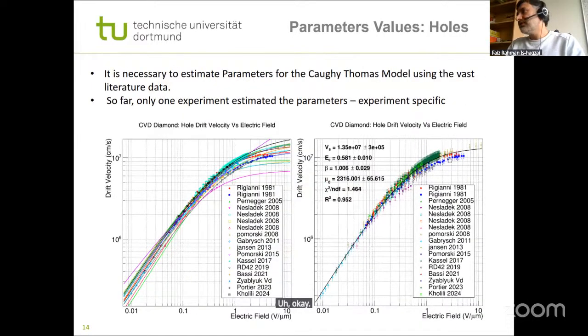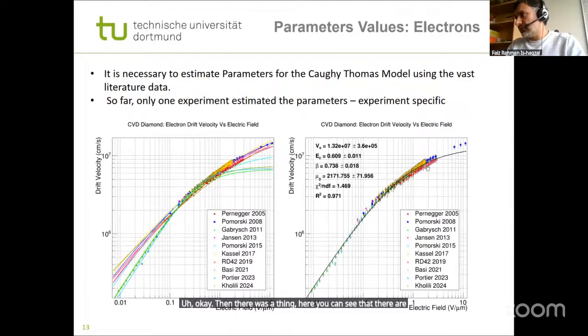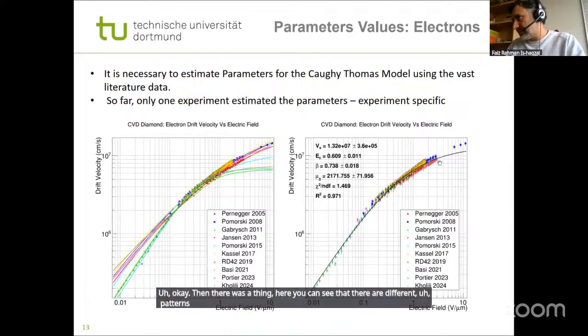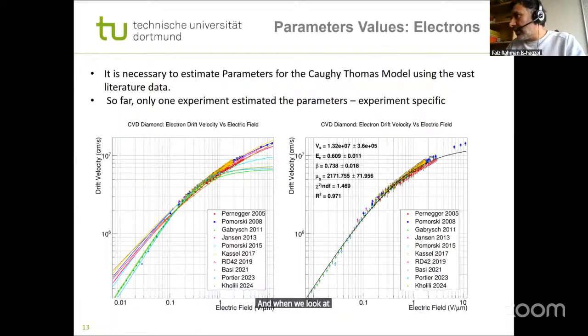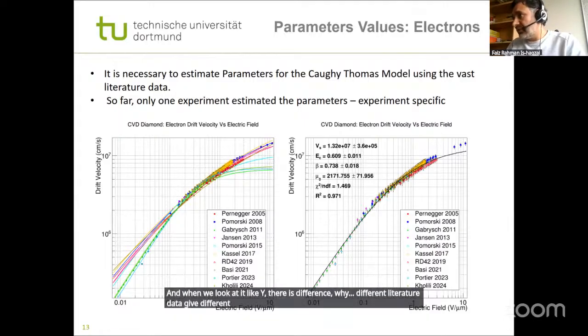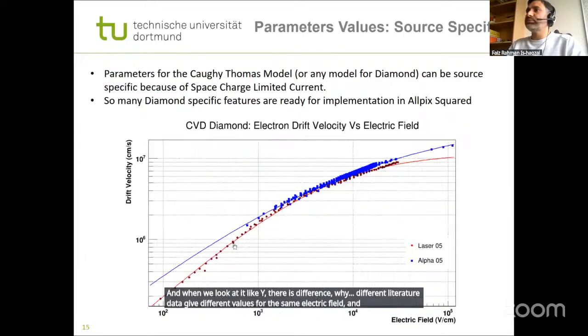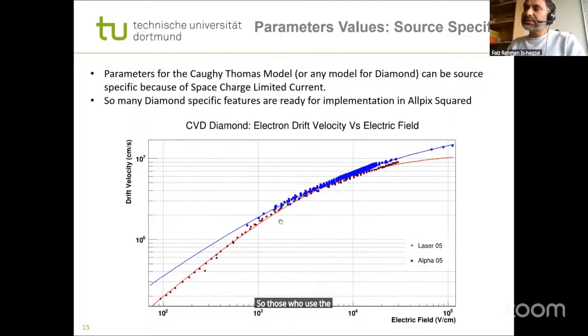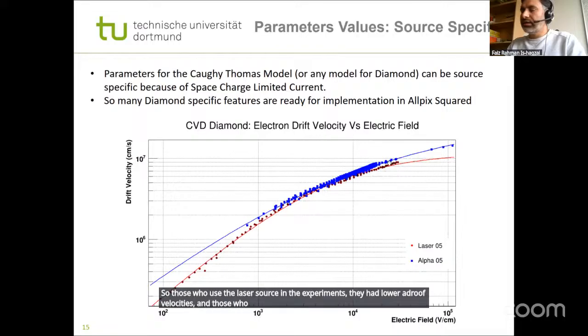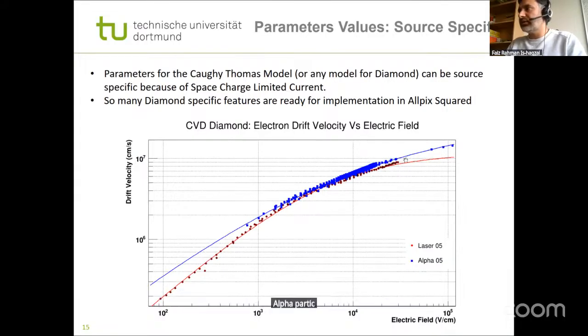Then there was a thing here: you can see different patterns, these blue lines and red lines. When we looked at why different literature data give different values for the same electric field, we found it's because of the source. Those who used a laser source in the experiments had lower drift velocities, and those who used alpha particles got slightly higher velocities.